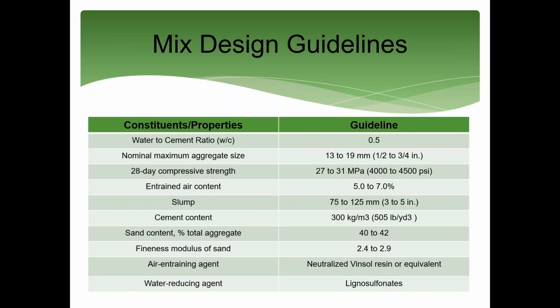This chart is a summary of the mix design guidelines as found in TP96. During the task force research, survey respondents indicated that agencies using these guidelines to prepare the concrete mixing for testing were able to produce a mix that was successful in holding up to the testing conditions. These guidelines were reviewed by other agencies with freeze-thaw tolerant mixes and found to be similar. The task force decided to move forward with these guidelines as the mix design guidelines for the work plan.